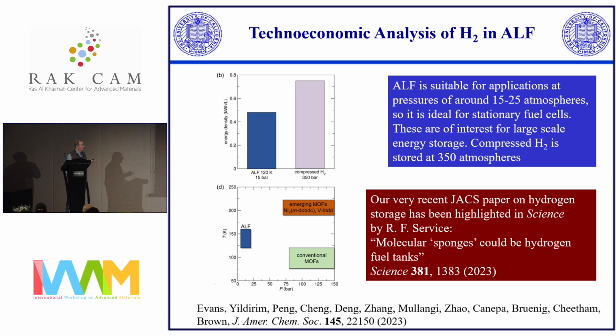If you look at the figure on the bottom left there, this is where ALF is best for hydrogen, sort of intermediate temperatures and low pressures. The kind of conventional MOFs are over here, and then some of the more specialized ones are up here. But when you have large cavities, you need more pressure. And so this is a case where having small cavities gives you an advantage and better absorption at low pressure.